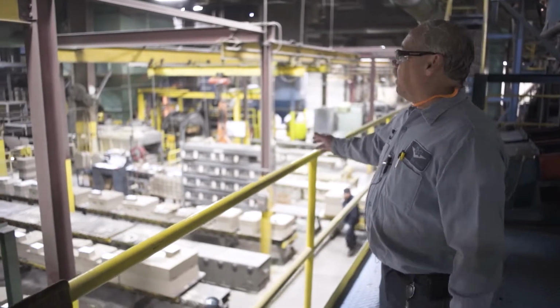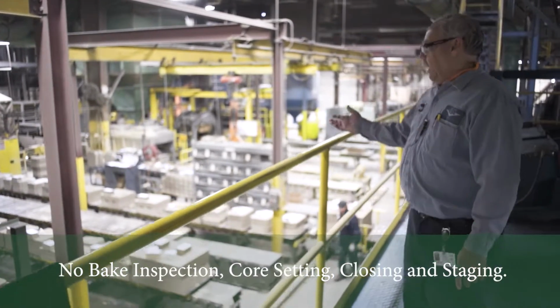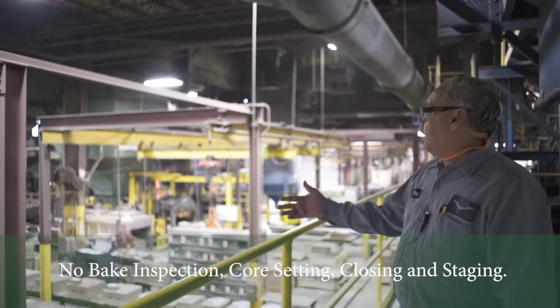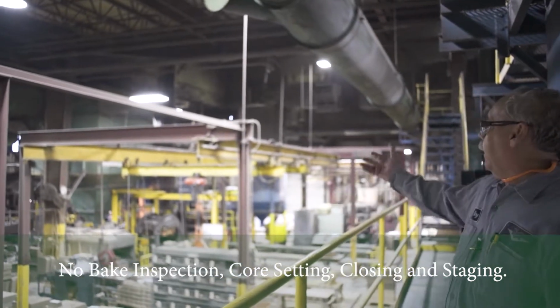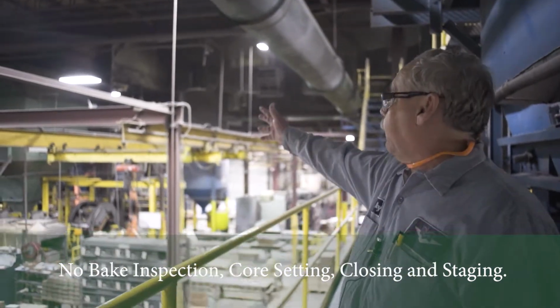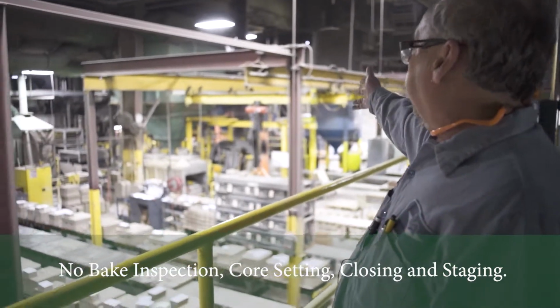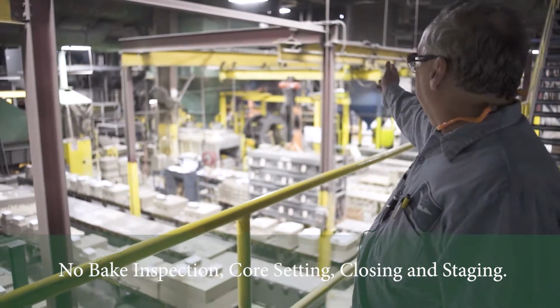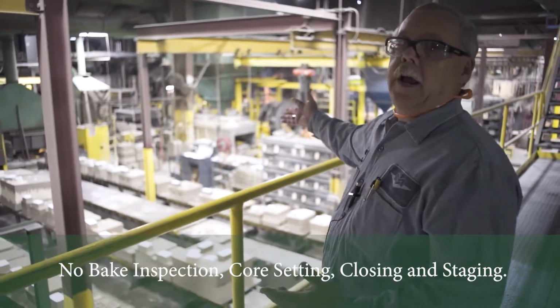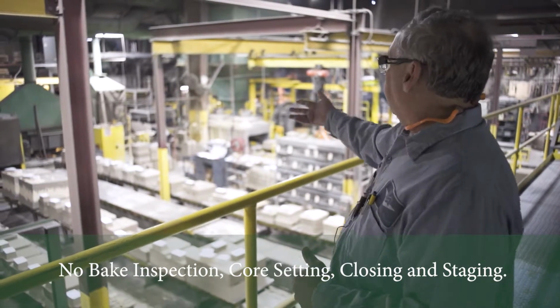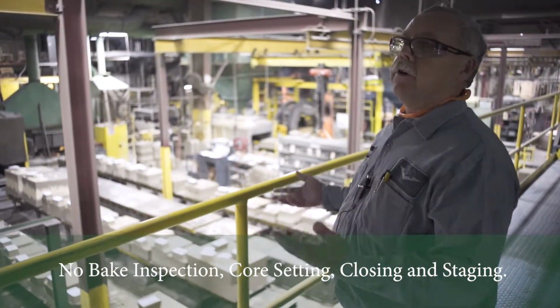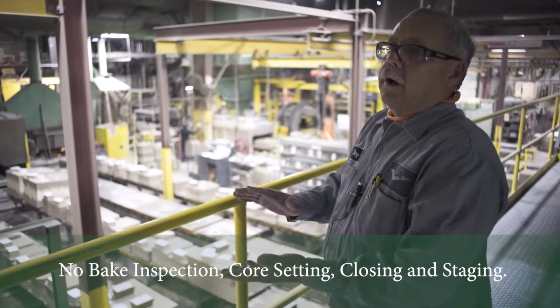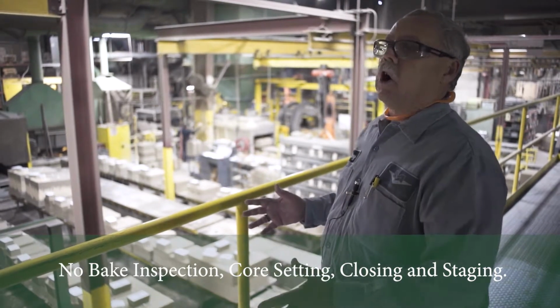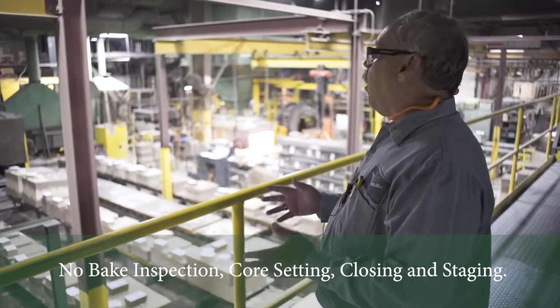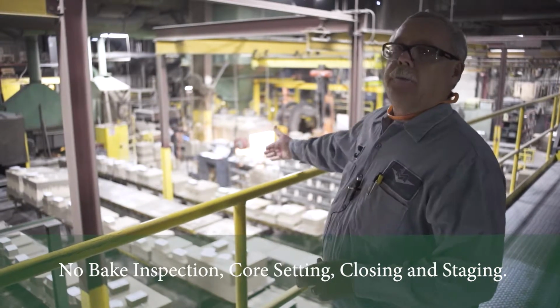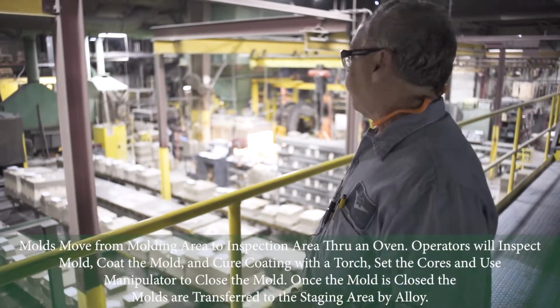Over here, you get an overview of our molding line. We have a molding line in the distance, far corner. It comes out of the rollover and goes into an oven for curing. From there, it goes to our molding line where we do the inspection. They'll coat the mold, dry it off with a torch, and then they'll set the core and close the mold and put them into our staging area.